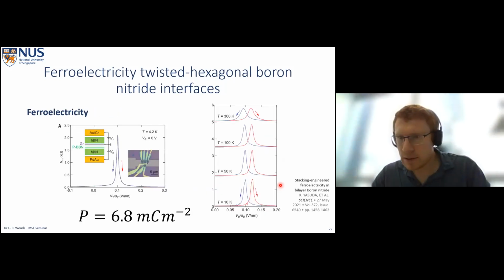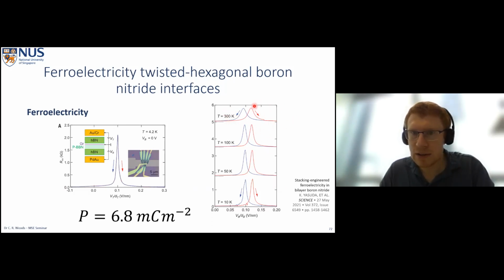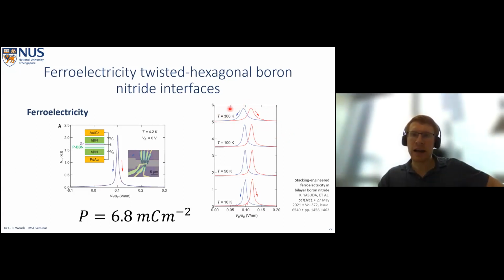So this is when I have to give a little bit of bad news. During the pandemic, we were actually scooped on the ferroelectricity part of this. So I have to mention that these other guys were able to do this nice experiment where they looked at single AB or BA domains, and they were able to, using an electric field, change the direction of this polarization. So what they're doing here is they're just measuring the main Dirac point in graphene, which they place adjacent to their twisted bilayer. And when they put a strong enough electric field, they can actually shift the main Dirac point.